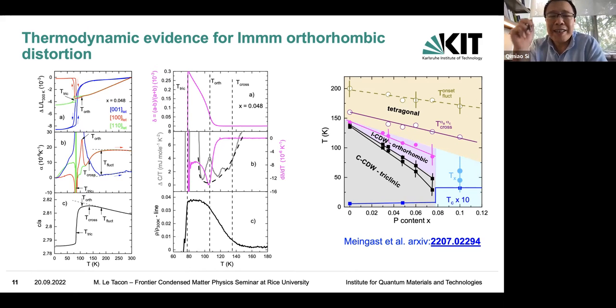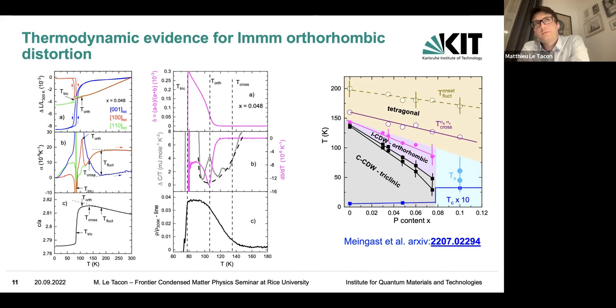I actually missed Jean-Pierre's talk, so maybe a bit of study from scratch. If I understand correctly, there's no thermodynamic nematic phase transition, but there is static CDW order. Is that the correct statement? There is something that looks pretty much like static CDW order, yes. And there is an elastoresistivity signal associated with this buildup of the CDW correlation, but there is no diverging electronic nematic susceptibility à la iron-based.